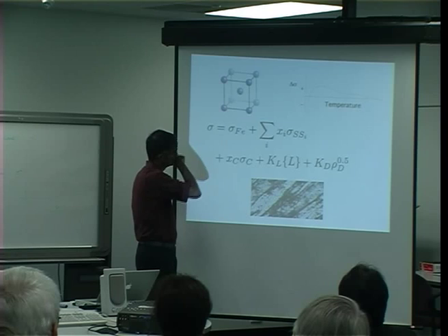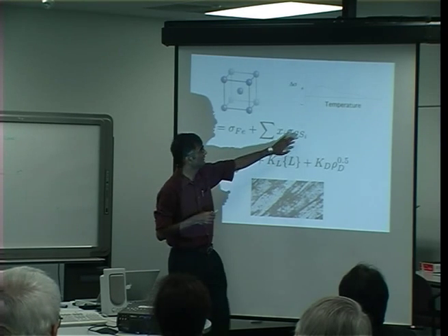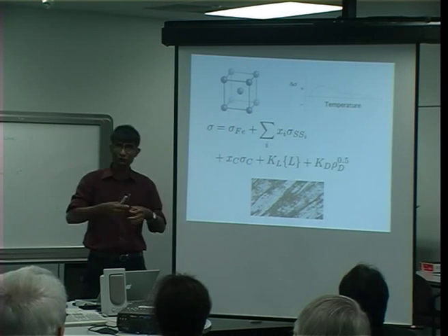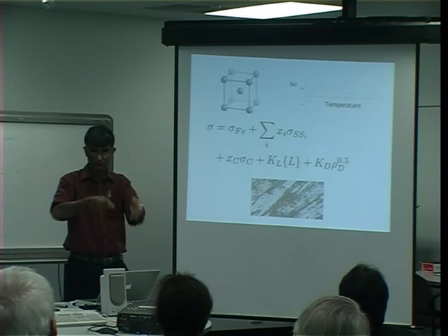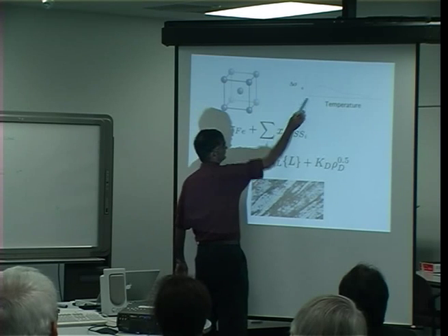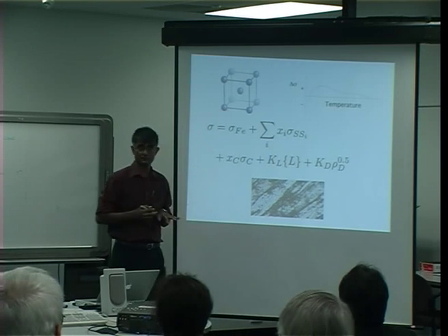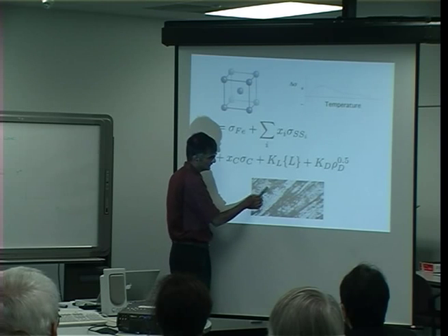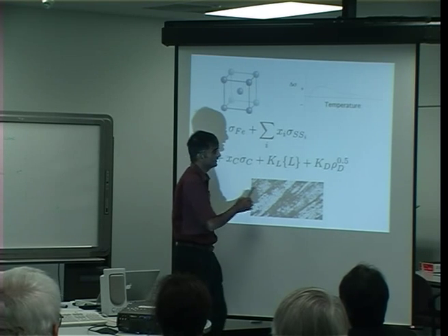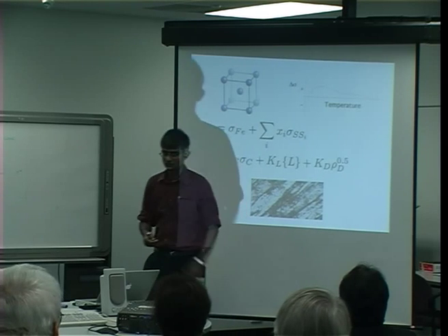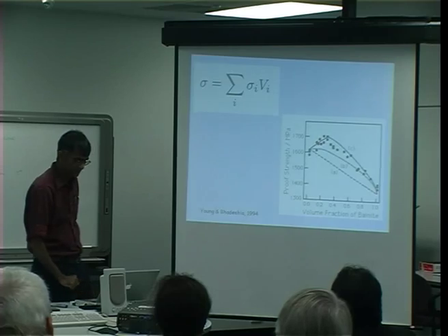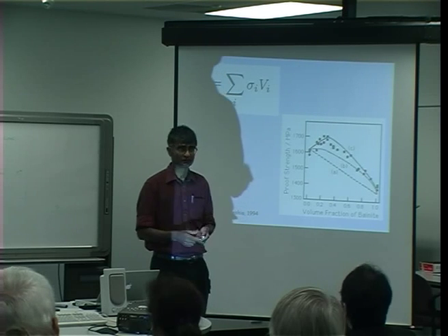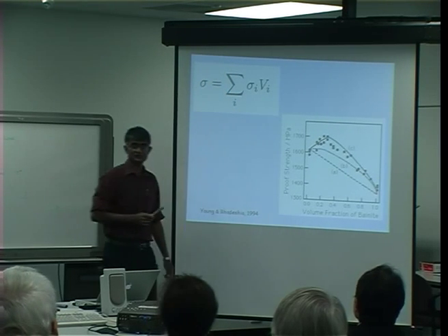So we've got that. We know how elements, solid solutions, strengthen as a function of temperature. So that's how they do it. At low temperatures, they actually help the dislocation to move by introducing a perturbation which allows them to move over a barrier. So you get solid solution softening at low temperatures. And carbon has a different kind of a solid solution strengthening effect because of the holes in the lattice. So all this knowledge is available. You then have the grain size strengthening, and you might have defects in your microstructure which give you strength as well. All of these things can be calculated for a single phase. You then need to combine the different phases together. And the simplest thing is to use a rule of mixtures.